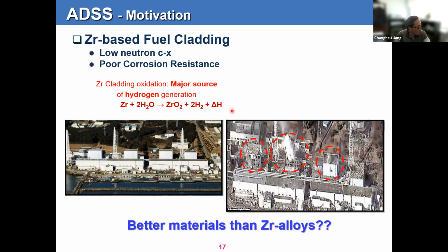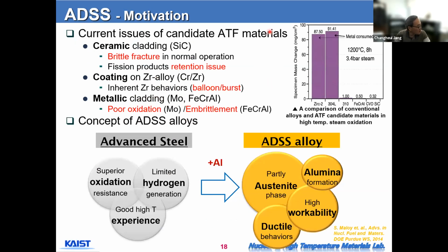So after the Fukushima accident, the nuclear industry and community were talking about whether there is a better material than zirconium alloys for use as cladding. The concept of a better cladding material is the so-called ATF materials, the accident tolerant fuel cladding materials. Several different materials have been proposed, and all of them have excellent high temperature corrosion resistance. This is one of the test results showing that, compared to the zirconium alloys and simple stainless steel, many of those proposed materials have very low weight gain. So it has excellent corrosion resistance. But unfortunately, this one is ceramic. This is a coating, so it has limitations.